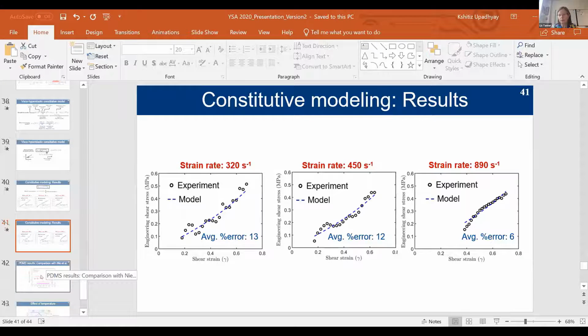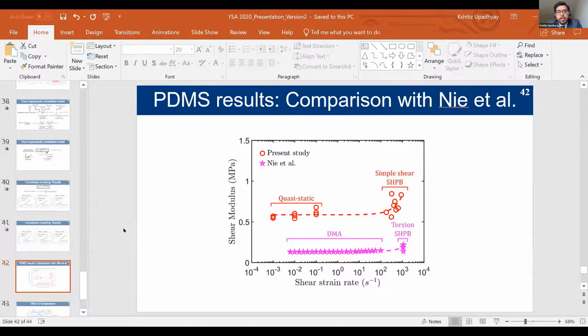That slide you showed... Yeah, I think like this. So this is something that is very common in dynamic experiments. In the quasi-static regime, the system is in equilibrium. There are no viscous effects in the system. There is no viscous overstress in the system. So these polymer chains are equilibrated at every point of time during the course.